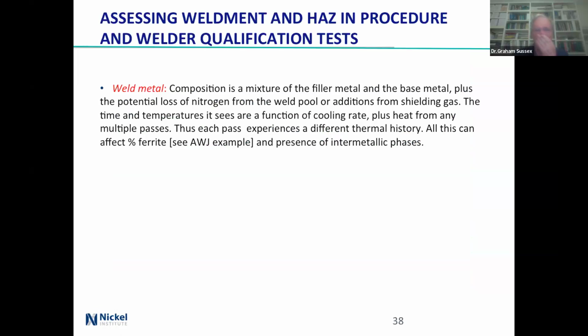All right, so assessment of the weld metal. In the weld metal, it's a mixture of the filler, the base metal, and whatever nitrogen has been taken up from the weld pool. If your shielding gas has nitrogen in it, or if you're welding a pipe and you've got purge gas with nitrogen in it, then you'll get nitrogen taken up and that will help to give you austenite.